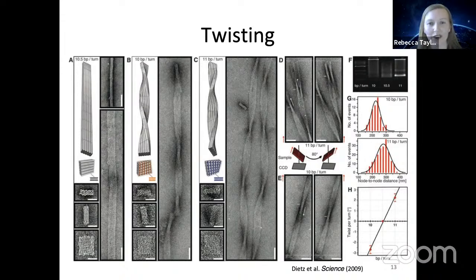But now if we have regions that are too short, where on average the crossovers are spaced more closely, at about 10 base pairs per turn instead of 10.5, you can see that you now have a twisted structure, right? And it's a left-handed helix. This comes from the fact that DNA is right-handed, so if you have too little, you get a left-handed torque. So you can get twist, and you can do the same by having too many bases and get a right-handed helix, right? And so you can actually control the level of twist.